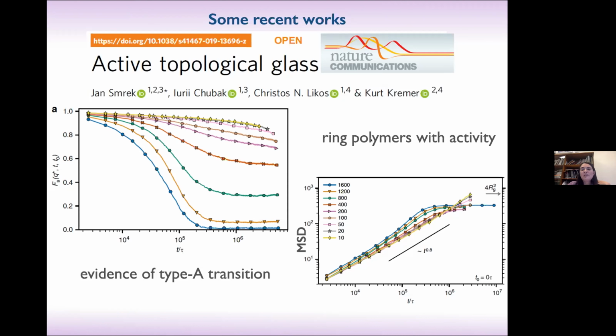They have found for these ring polymers, as a function of activity, the onset of a glass that occurs with a type A transition, this sort of localization transition. They found the occurrence of subdiffusive mean square displacement, and they say in their paper that perhaps there is a nearby higher order singularity. So I think that the fact that such a recent work on a very hot model gives hints of anomalous dynamics, it would be really nice if we can apply the ideas of 20 years ago to these new models in the new simulations that we will do.